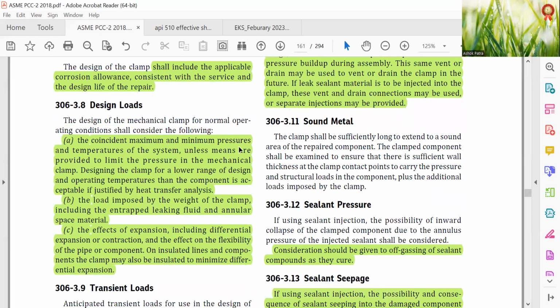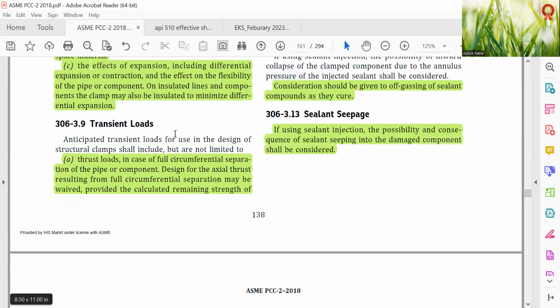Consider the coincident maximum and minimum pressure and temperature of the system, unless means are provided to limit the pressure in the mechanical clamp. Designing the clamp for a lower range of design and operating temperature than the component is acceptable if justified by heat transfer analysis. Consider the load imposed by the weight of the clamp, including the entrapped leaking fluid and annular space material, and the effect of expansion, including differential expansion or contraction, and the effect of flexibility of the pipe or component. On insulated lines, components of the clamp may also be insulated to minimize differential expansion.